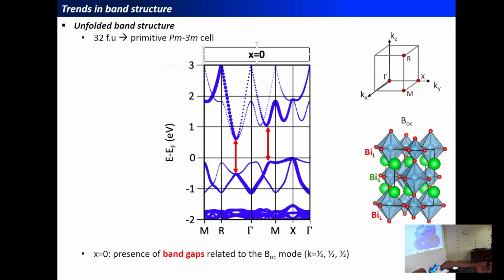The gaps along the gamma-R path, which in fact is between the gamma point and the R point of the Brillouin zone, which is just the path related to the symmetry of the breathing distortion, along the 1,1,1 direction of the cubic cell of the material. And you see that there is a sizable gap opening due to the appearance of the breathing distortion in the material. And now we can try to follow what's happening when we put more and more holes in the material.